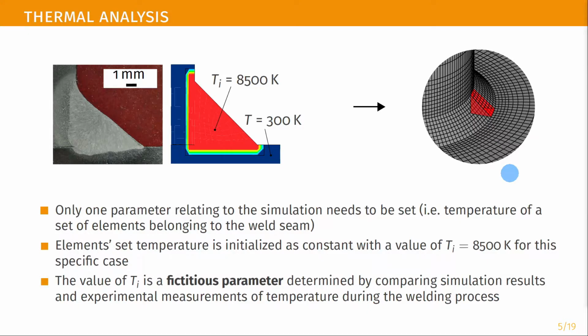The value of Ti was set for this particular case at 8500 Kelvin. This value has been obtained from the comparison of experimental and numerical temperature results by directly calculating temperature around the weld bead. Specifically, Ti does not represent the melting temperature of the base metal, but instead it is a fictitious parameter that incorporates all the assumptions that this model includes.